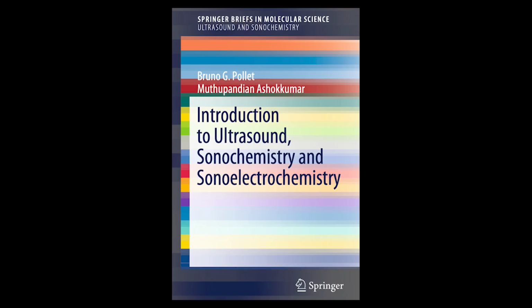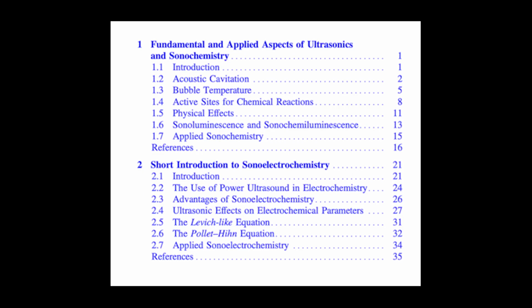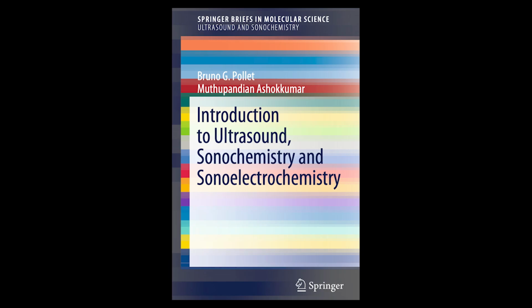There's a related effect useful for seeing where the action is: sonochemiluminescence, SCL. This happens if you deliberately add a chemiluminescent substance like luminol to the solution. Luminol, like they use in forensics, glows when it reacts with certain oxidizing species. In sonochemistry, the OH radicals generated by the collapsing bubbles react with the luminol, and that reaction produces light. So the light comes from a chemical reaction triggered by the radicals, not directly from the heat. Correct, and the advantage is that SCL is usually much brighter and easier to detect than the faint SL.